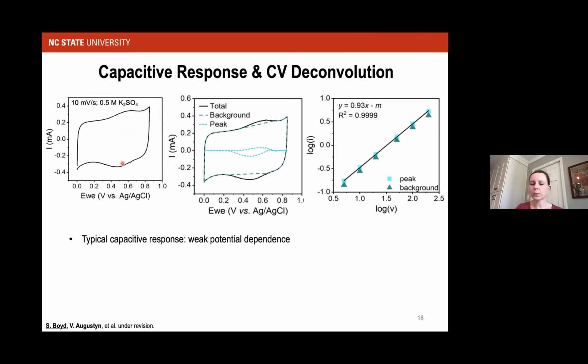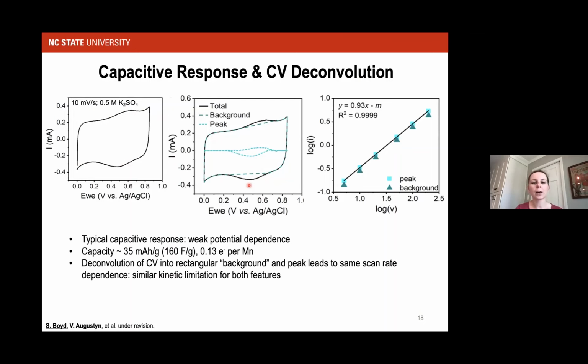Here's the electrochemical response. We see it has that very typical, potential-independent for the most part, response. We do see some broad peaks that are present. When we try to deconvolute them from the background, which is really the predominant part of the current, we find that they actually show very similar kinetic dependence, which suggests to us that they have similar kinetic limitations. They're probably due to the transport of similar species, which we think, at least from what we know so far, are potassium cations. Should also point out that the capacity we're talking about here is very modest by standards of lithium-ion batteries. So we're talking about 0.1 electrons per manganese. And the question is, is this just induced charge, or is this actually a redox event that's taking place in the birnessite?